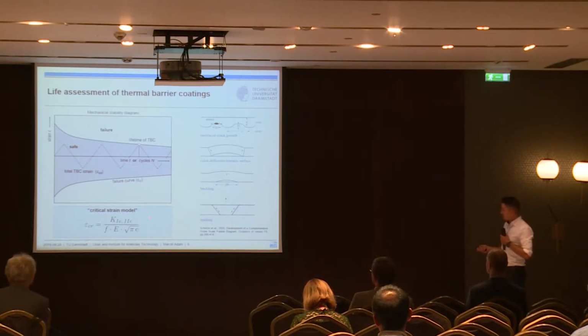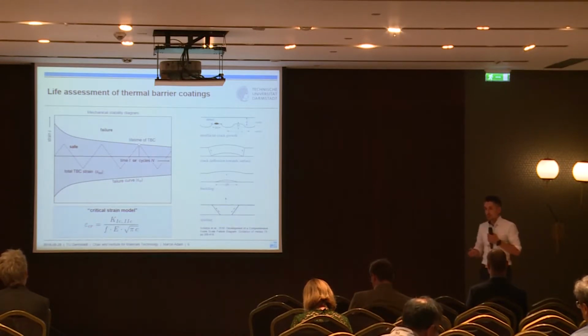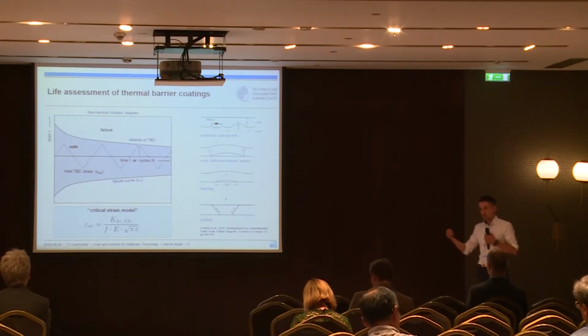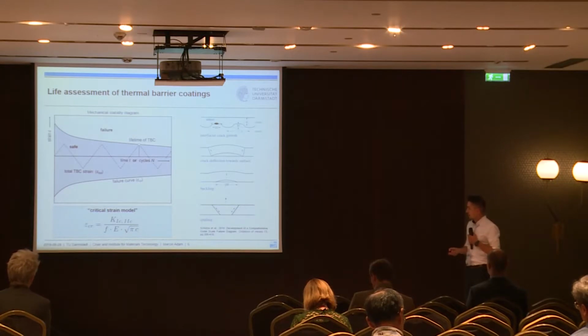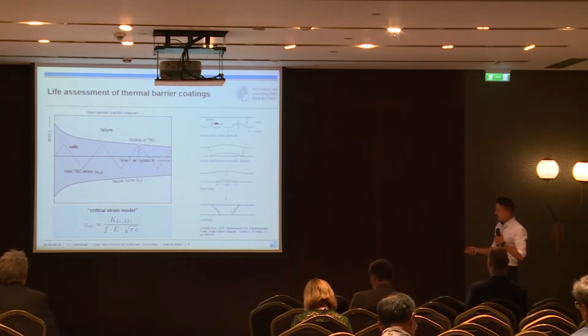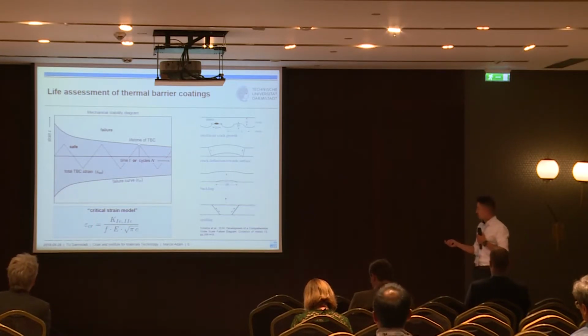So in our studies, we use a mechanism-based model, which is mainly based on the Griffith criterion to describe the failure of brittle materials, and has been modified a little to get the critical strain as a parameter which describes the lifetime. It wasn't modified by us, but by colleagues from the research institute in Frankfurt, I think 10 years ago. That's the main parameter we use to assess the lifetime of our double-layer coatings in the next slides.